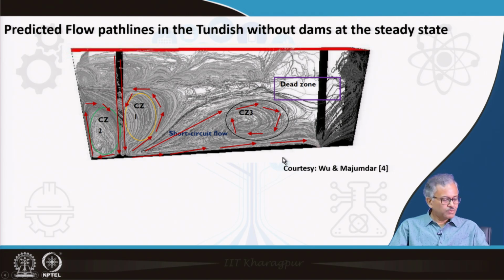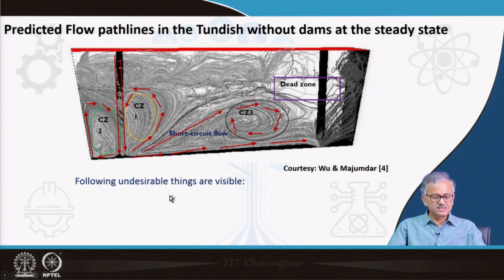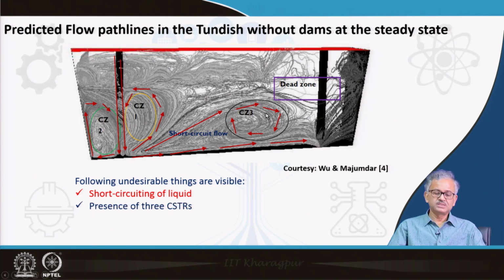What you can find in this case are the following undesirable things. One is short circuiting. And the presence of three big CSTRs, and CSTRs are not desirable in a tundish at least. It is good from the mixing point of view, but in a tundish it is not desirable, because as I said, the liquid stays in the mixed reactor for a wide distribution of residence times. So they report to the exit stream at different times, and the temperature of the exit stream will be different, which is not desirable.